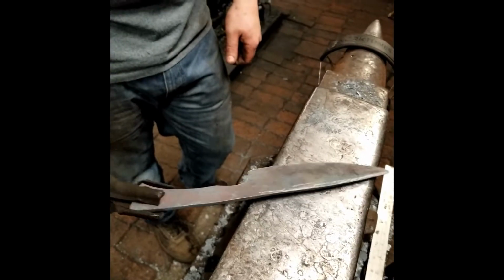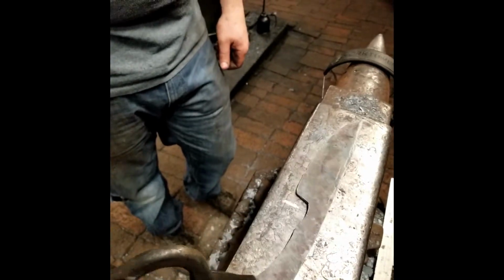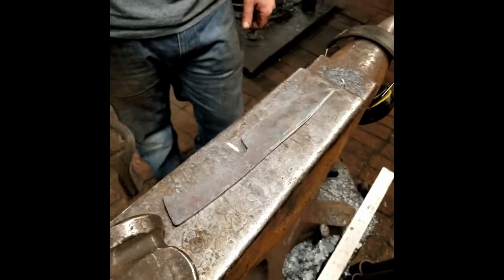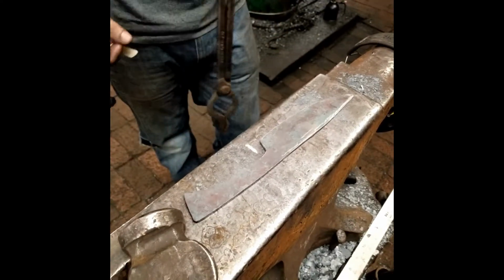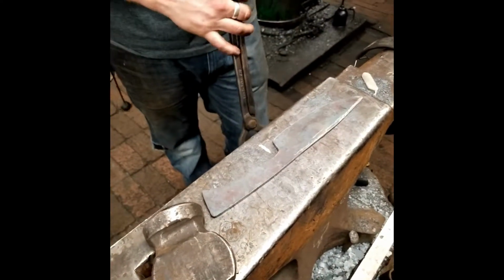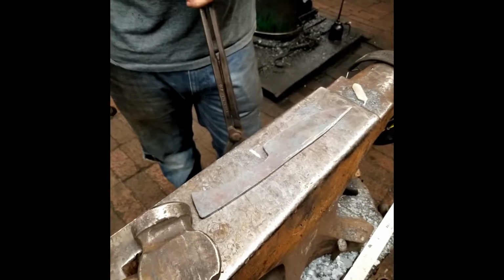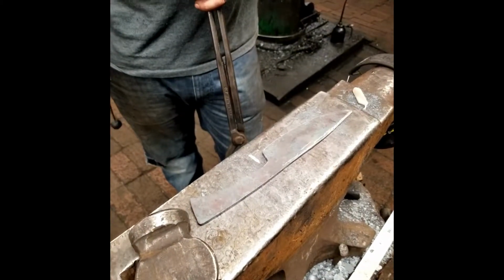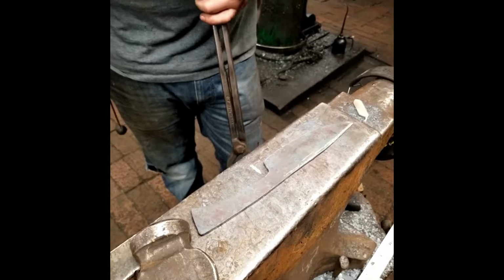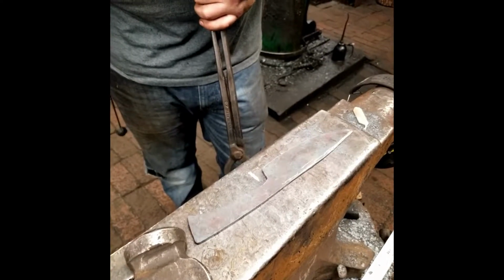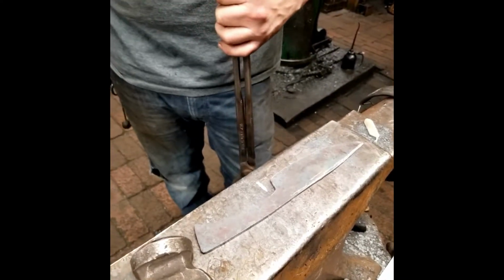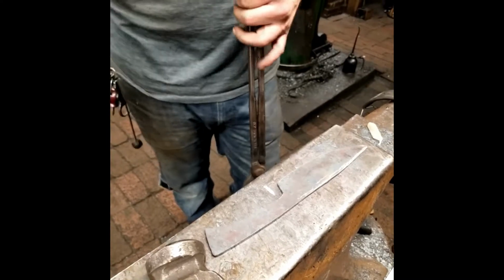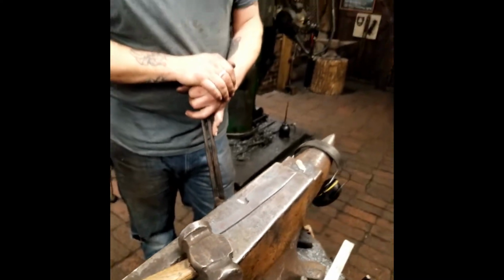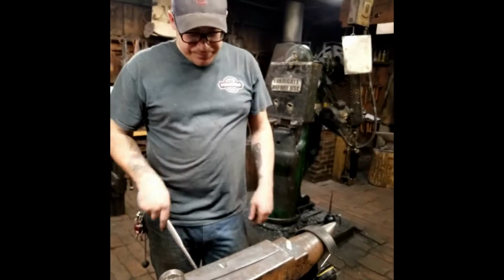And so with this, are you going to do an oil quench? 1080 is oil quenching steel. I did use Parks AAA until I spilled it all, so now I use vegetable oil. You heat it up to 130 degrees, and then you quench it once it's at critical, which is past non-magnetic. Yep. And then you quench it.